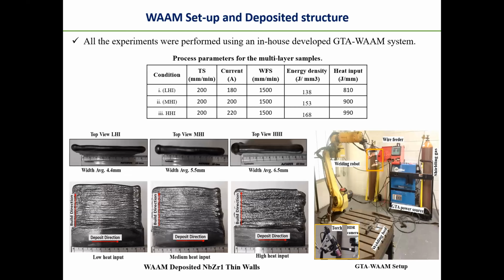So we deposited 3 thin walls of niobium zirconium alloy with GTA-based AM. We changed the arc current, varying the energy density and heat input. As the heat input increased, our energy density increased, the wall bead width increased, and the wall height decreased some. This is because at higher heat input, the molten pool has much more fluidity due to the lower viscosity and surface tension.